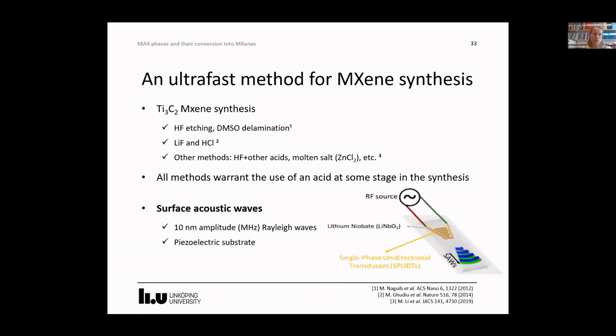We have most recently discovered that MXenes can be synthesized in a few milliseconds without the need for acids by using surface acoustic waves. So surface acoustic waves are 10 nanometer amplitude Rayleigh waves of a megahertz frequency, which are generated, confined to, and subsequently propagate along the surface of a single crystal piezoelectric substrate.